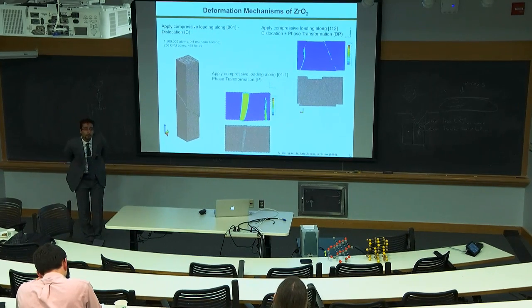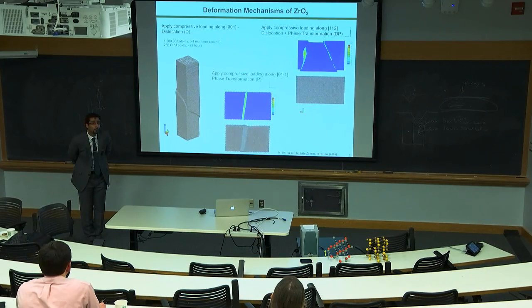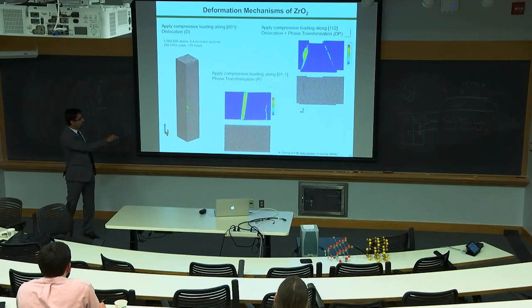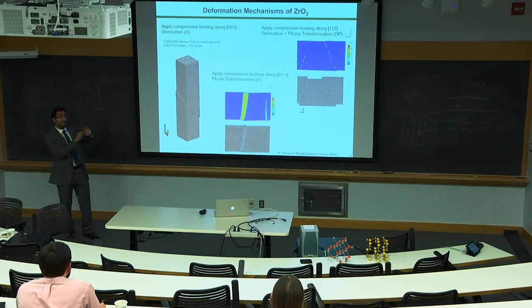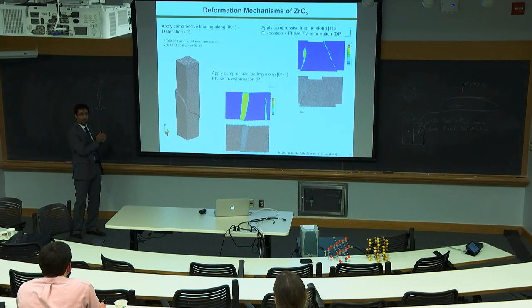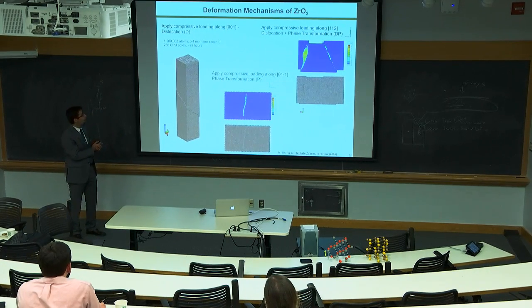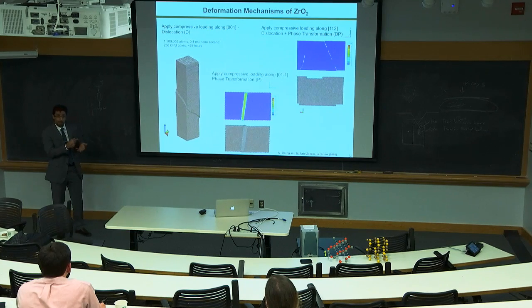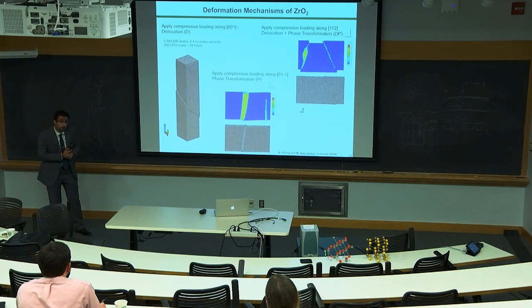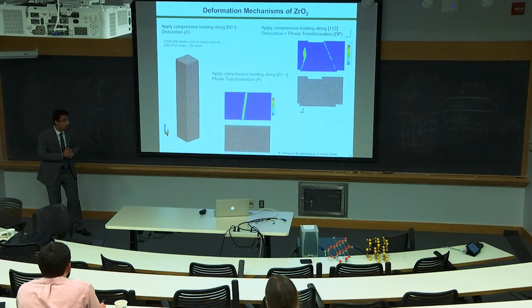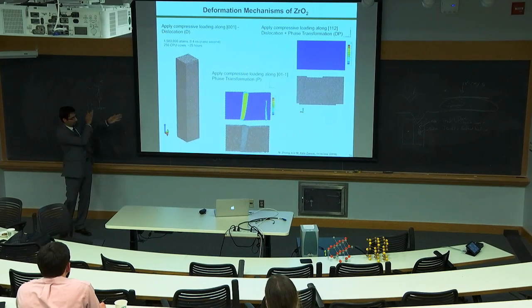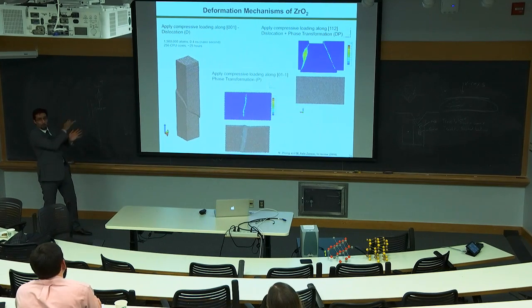Are you essentially nucleating a dislocation on that slip line? For this one, yes. Initially we don't have any nucleation or any defects. This is a perfect single crystal, actually a column, and when you deform it, it will happen by itself. So we are not initiating any nucleation ourselves. Can you see the dislocation nucleate somewhere, or does the slip plane move evenly? We have actually identified the nucleation of dislocation first. If we zoom in on this plane, we initially see a dislocation, but eventually it will look like a complete slip.